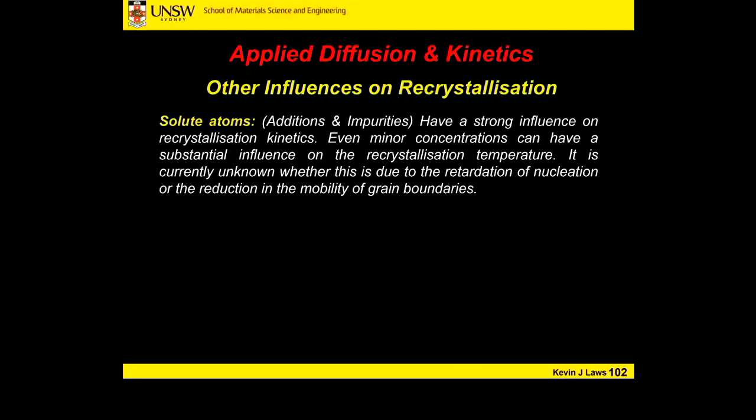Basically, if we have a solute element, something that we introduce to our metal, typically dislocations will become tangled or hooked up on that solute element as they're trying to pass through our material. If we have a different size atom on a site, that imposes strain fields in the lattice. Dislocations are also putting a strain field in the lattice because they're a defect. Defects will attract one another to try and cancel out those strain fields, so dislocations become attracted to defects.